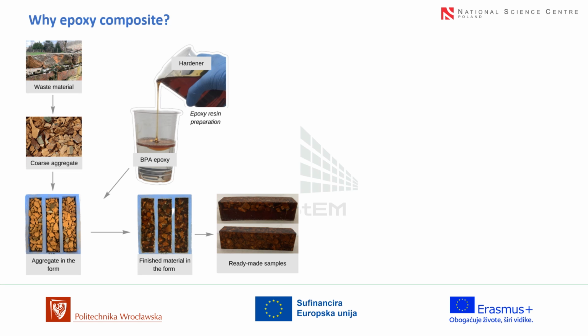Well, you can observe how it was all done. We used old waste material in terms of bricks, then used it as a coarse aggregate, which lands into the aggregates in the forms especially prepared. Then the liquid mixture of epoxy resin with hardener is cast into the molds. That finish results in a dense, highly durable synthetic stone or synthetic material.